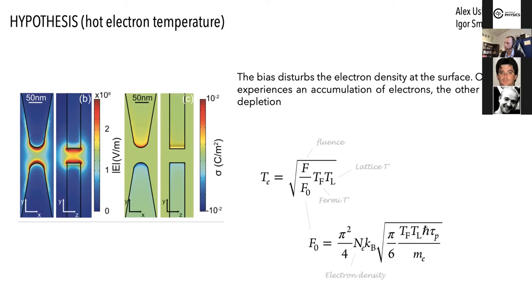And it turns out that the electron temperature in the system depends on many parameters. It depends on the laser fluence, the lattice temperature, the Fermi temperature, but it also depends on this parameter, which, without going too much into detail, is proportional to the electron density. So you can appreciate that the electronic temperature now scales with the inverse of the square root of the electron density. The hypothesis for us is that very locally here we have a change of this electron density, either a positive change, where we have more electrons, or a reduced number of electrons on the positive side of the bias.